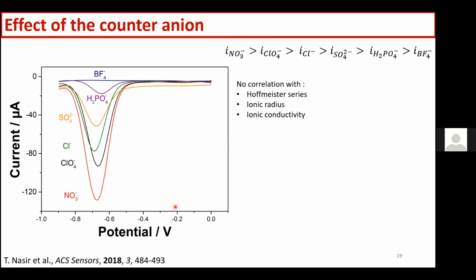We also looked at the effect of the counterion. When these organic cations are going inside the pores, they are accompanied by their counterions. So if we use sodium BF4- as an electrolyte, BF4- is a rather large anion, and we absolutely have no signal. We cannot reduce the paraquat. And then if we change the ions, we can see that depending on the ion, we have quite a large distribution of peak current.